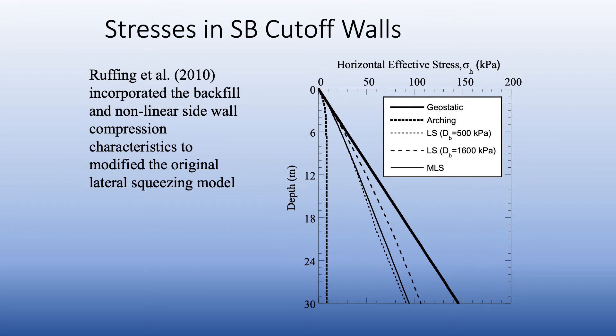The arching model was later quantified and shows very low stresses in the trench. However, that model assumes rigid sidewalls. Professor Filz from Virginia Tech recognized that the sidewalls move inward, causing lateral squeezing of the backfill. Daniel Ruffing at Bucknell University then modified that model to incorporate the compressibility characteristics of the backfill into what is called the modified lateral squeezing model.